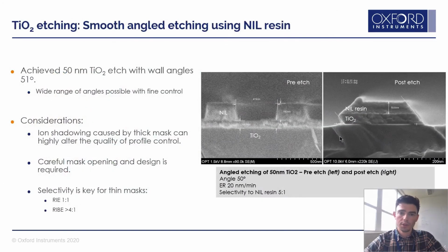And this is what we achieve. On the far right hand side, we can see an SEM image of a lovely 50 nanometer titanium dioxide grating with parallel walls around 50 degrees. This wall angle is manipulable with fine control. You could go up to 90 degrees and do your normal binary grating, or you could even come down more acute. These walls should be nice and parallel and with a good quality surface, but we do need to have some considerations there.